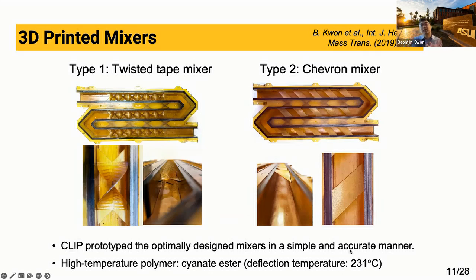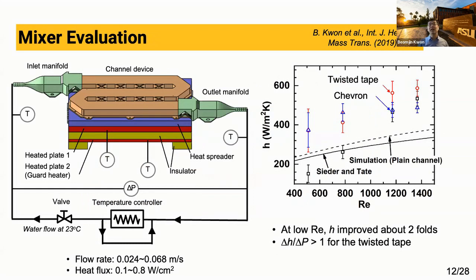So this can be used for some mild cooling applications. Right. So of course, we tested the performance of the optimized cold plate, and here I show the experimental results showing the convection heat transfer coefficient versus the water flow Reynolds number. And the dashed line and solid line here represent the data from plain channel without any static mixers. And here I show the data from the channels, including static mixers. So we were able to increase the convection coefficient more than twice.